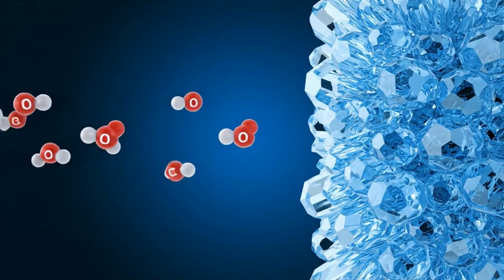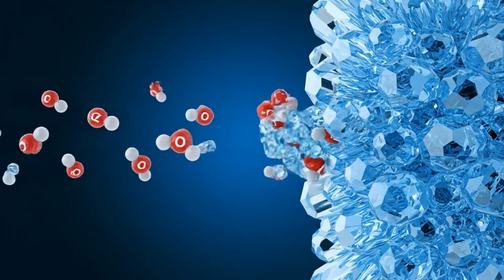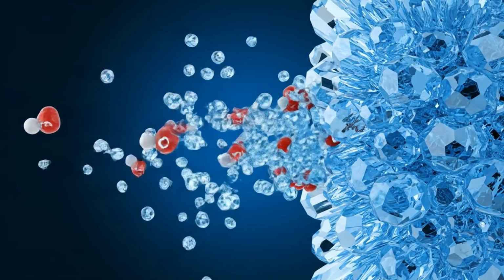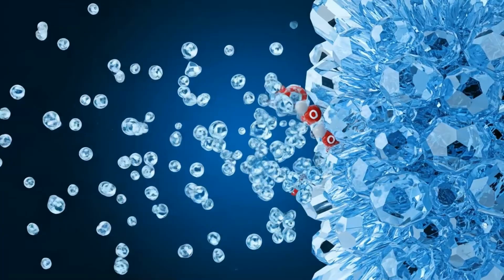Porosity measured below 5% compared to 15 to 20% in standard concrete. Lower porosity means water can't penetrate. Less water means longer life. But the real test came next. Could it actually heal itself?